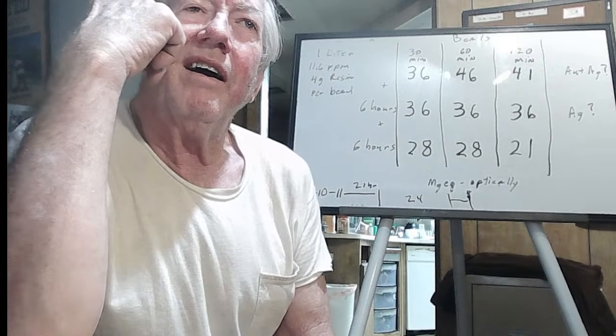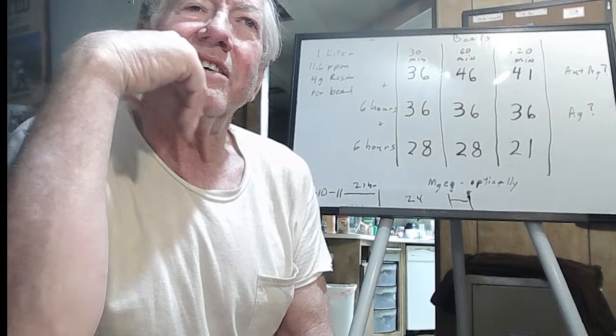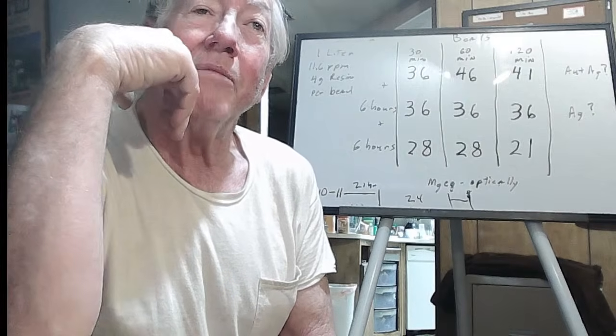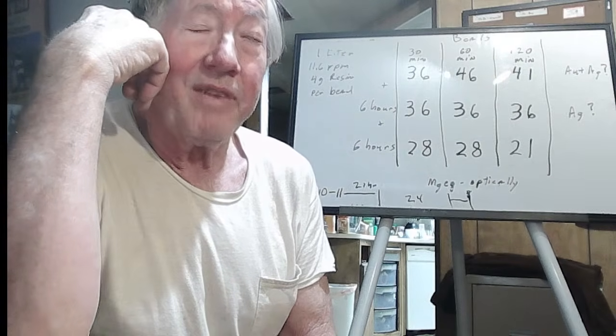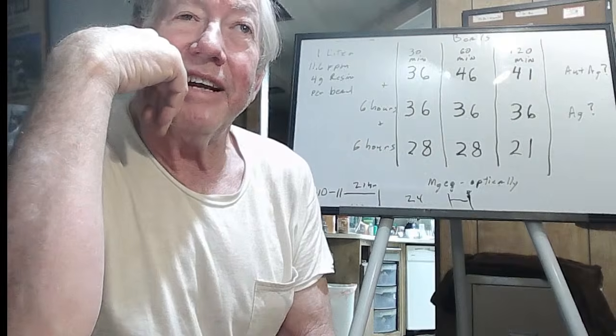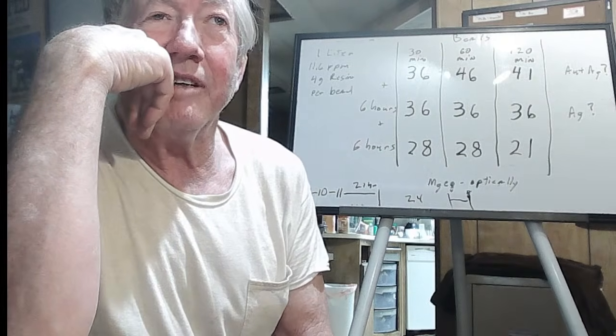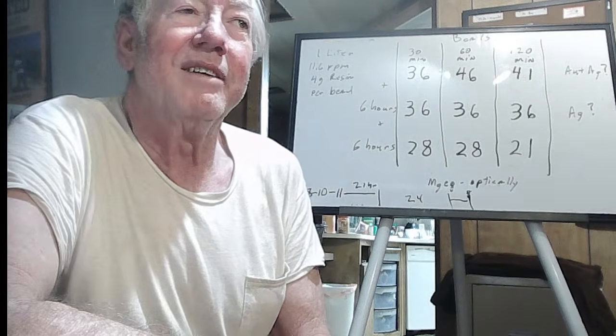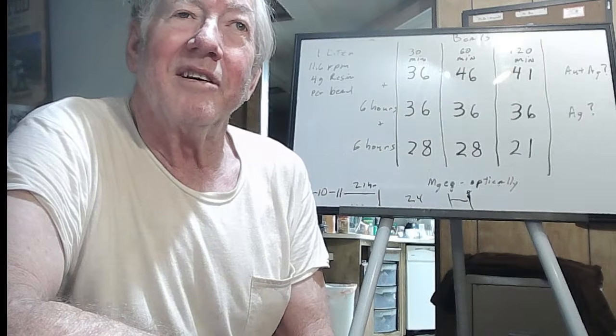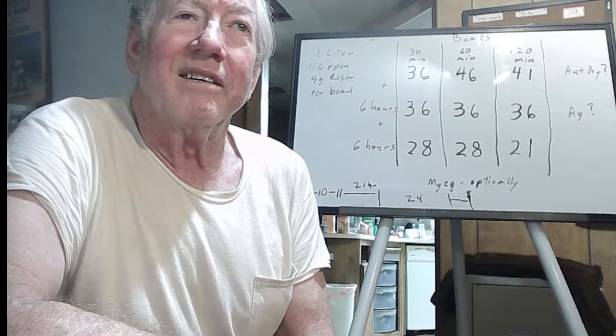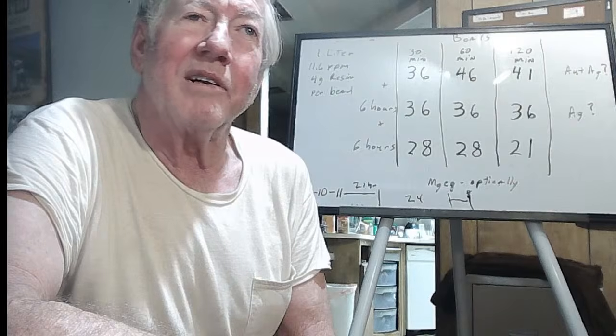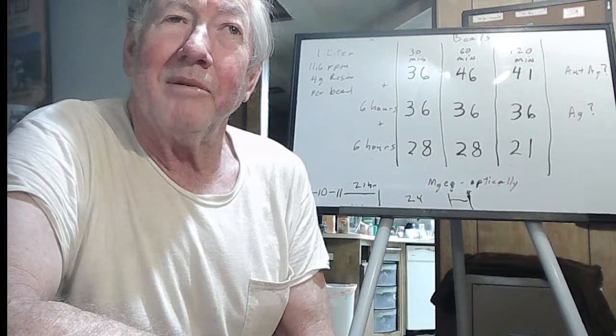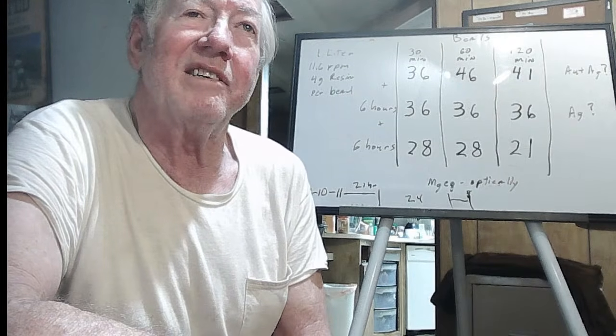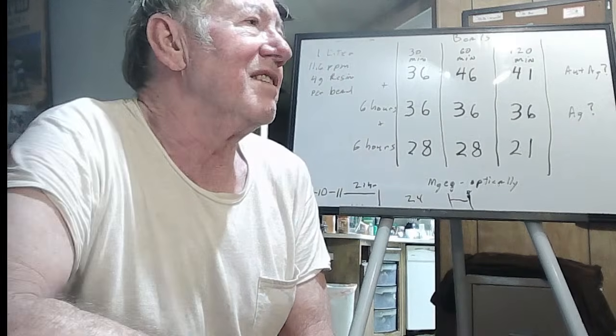Well, in terms of dissolving the gold, not much. In terms of resin and pulp, theoretically, absolutely. There's going to come some point where the equilibrium just goes to heck, but you should be able to get down to 3 parts per million without too much trouble. But it might take a couple iterations of putting the resin in first.